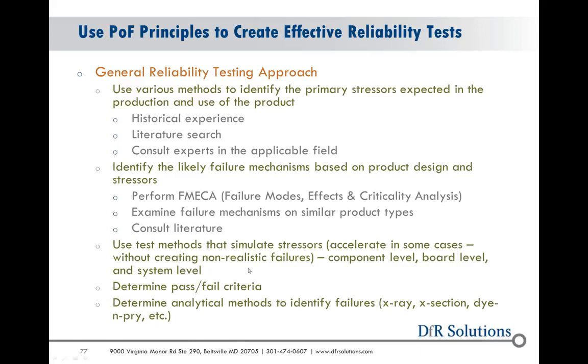Use test methods that simulate the stressors, whatever those are. Test at various levels — component level, board level, system level. Determining the pass/fail criteria and clearly specifying that is also key. Don't just check electrical functionality because many tests will pass functionality but have a ton of damage internal to the board. You may have fractured traces still touching that function but would be an intermittent failure in the field. Performing some amount of analytical failure analysis afterwards is highly recommended to understand what damage has occurred as a result of the test.